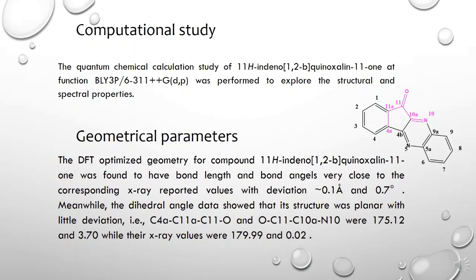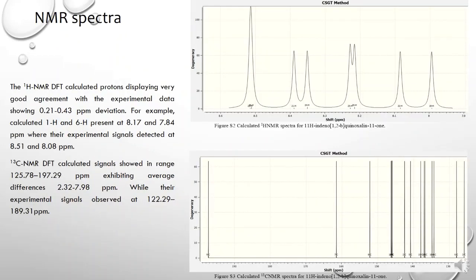175.12 and 3.70 while the X-ray values were 179.99 and 0.02. NMR spectra: there is agreement between calculated and experimental proton NMR with deviation 0.21 to 0.43.